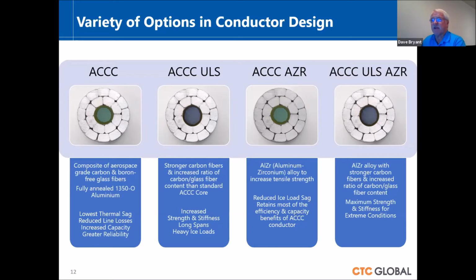The ULS conductor actually uses a higher grade carbon, and the ratio of the carbon to the glass is increased from 50-50 to 70-30. So it's got a higher modulus, a higher strength. It's about twice as strong as HS 285, if you're familiar with the product, the high strength steel. So it's quite a bit stronger than high strength steel. And again, it's about 70 or 80% lighter, which again allows us to use trapezoidal wire to get more amps